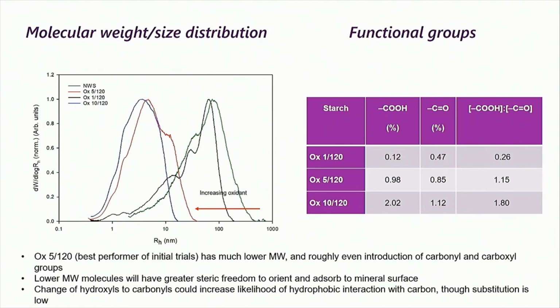Now, determining if it's the molecular weight or the functional group changes that are really contributing to our improved results is a bit of a challenge. You've got very large molecules still with very subtle changes. You can see there, these are only talking about less than 1-2%, less than 1% type of changes. So in the scheme of things, it's not very much, and it's hard to imagine that could be that effective. But with the mechanism of the hydrophobic interaction, we're just trying to establish if that is exactly what is occurring. The carbonyl is slightly more hydrophobic than the hydroxyls, and that could be just enough to get it to adsorb to the carbon.